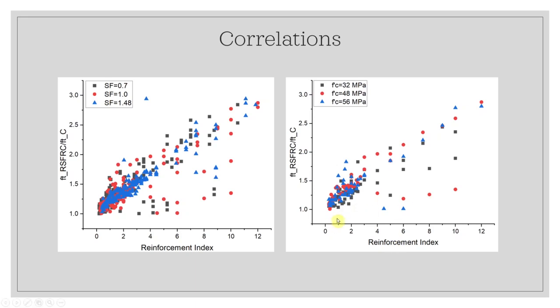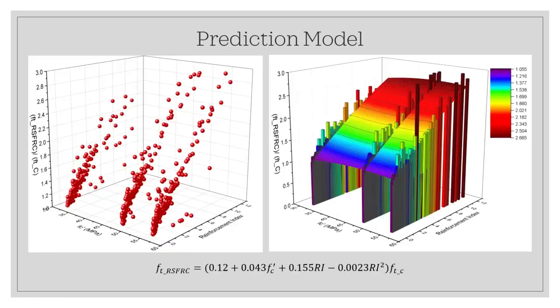But as you see, by increasing the reinforcement index, in most of the cases depending on the shape factors or the compressive strength, you see a significant increase in this ratio, which is the ratio between the tensile strength of recycled steel fiber reinforced concrete over the tensile strength of concrete. And after that, as a part of that result, which is still ongoing, these are showing some prediction models that were conducted based on the reinforcement index, FC prime, and the ratio between the tensile strength of recycled steel fiber reinforced concrete over the tensile strength of the concrete.